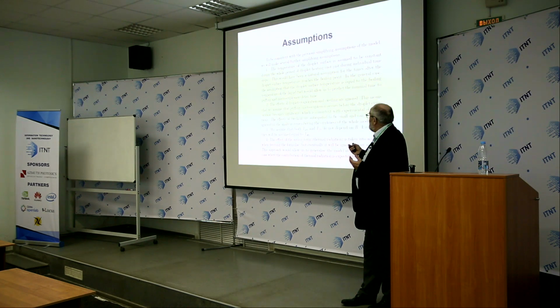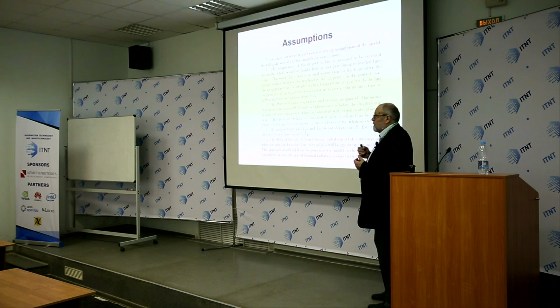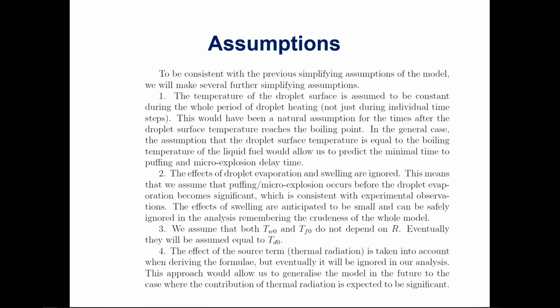And then we made a long list of assumptions. The first assumption was that the temperature at the surface of the droplet is fixed and doesn't change with time. Then we assume that the effects of droplet heating, swelling and evaporation can be ignored. Obviously, during the time of microexplosion, swelling and evaporation are relatively small. And then we can assume that initially the distribution of temperature inside the droplet doesn't depend on the distance from the center of the droplet. And the effect of the source term is taken into account initially, but eventually it was ignored.